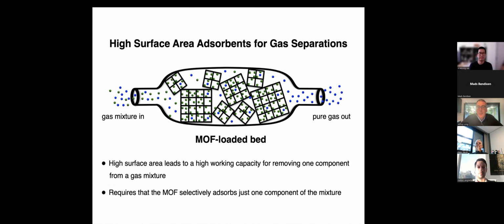So in terms of use, the simplest way for using one of these materials would be to load a column with the solid adsorbent, bring the mixture, say CO2 containing flue gas, in at one end, and as the gas runs through the material, it should selectively adsorb carbon dioxide and let all of the other molecules out the outlet at the other end. As you do this, eventually you'll saturate the adsorbent with CO2. And at that point, you'll either raise the temperature or lower the pressure and release CO2 in pure form for utilization or sequestration. And then you start again. And so these materials need to be able to sustain millions of cycles, ideally, for adsorption and desorption of the CO2.